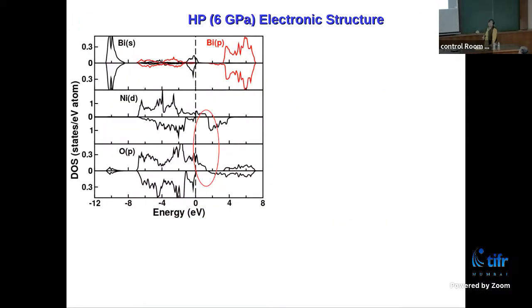Now, what happens at the high pressure? At the high pressure, there is only one kind of bismuth. You can see that it has this deep 6s state and no split of states, even if there is a little bit of something you can see because of the mixing with the nickel. Instead, the nickel electronic structure changes a lot, and it has these states which now have their counter states with the oxygen. Oxygen again becomes empty, but now it looks more like the nickel instead of the bismuth.